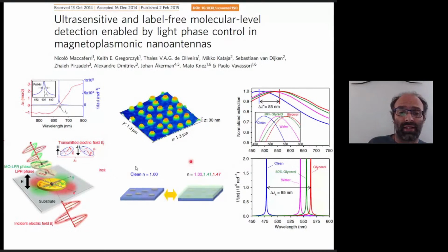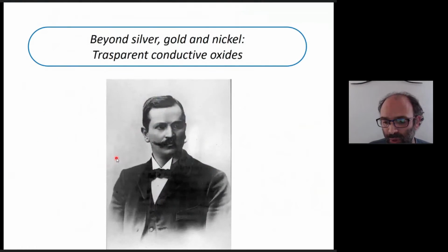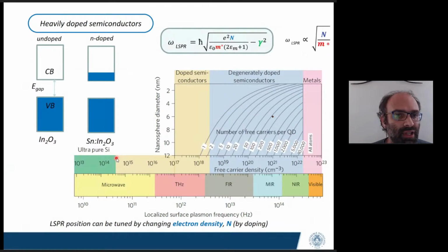But there's a big drawback: the nickel discs are very magnetic, so they respond strongly to the magnetic field. But unfortunately, they have very broad plasmon resonance, and this is terrible in terms of sensitivity. Okay, so what we propose here is to use heavily doped semiconductors, for instance indium tin oxide nanoparticles, with a resonance in the infrared, and use these as magnetoplasmonic systems.